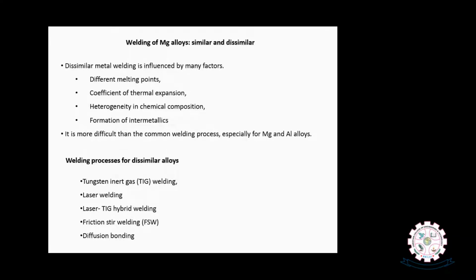and heterogeneity in chemical composition and formation of intermetallics from the alloying elements in the liquid state is another big challenge when we are joining dissimilar metallic systems. Among them, one, if it is magnesium, it is more difficult than the common welding processes, especially for magnesium and aluminum alloys. So the welding processes usually adopted for magnesium alloys are tungsten inert gas welding, laser welding, laser TIG hybrid welding, friction stir welding, and diffusion bonding.